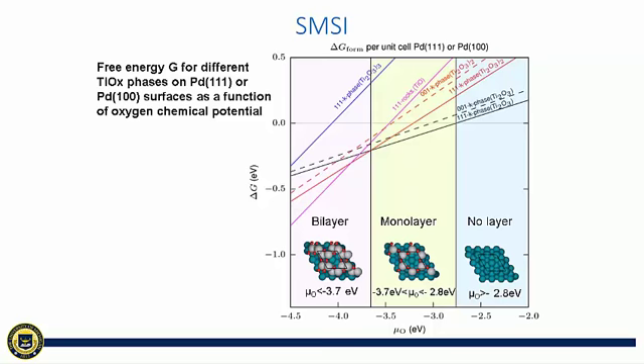After he finished his calculation, he asked me to confirm it experimentally. Because the gas cell we received was not capable of mixing gas, we designed a special technique to mix a little bit of hydrogen and a little bit of oxygen in the gas cell, and when the system reaches equilibrium, the corresponding oxygen chemical potential can be calculated. In the case of 5% hydrogen balanced with argon, it corresponds to an oxygen chemical potential less than minus 3.7 eV, and we did see the formation of the crystalline bilayer.